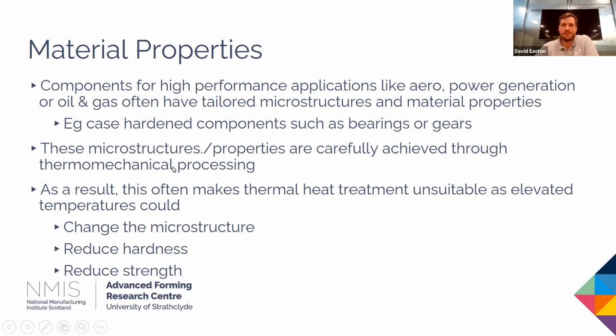And now this can raise a problem when you then need to reduce the residual stresses, because using heat treatment, you're also relying on thermomechanical processing. And you could be restricted in temperatures that you go to. If you go to too high a temperature, you can change the microstructure, you could reduce hardness, you could reduce strength. And this can leave a real issue whereby you can't stress relieve your parts because you can't raise the temperature high enough to achieve it. And this is, I'd say, a fairly common issue that comes up in manufacturing.